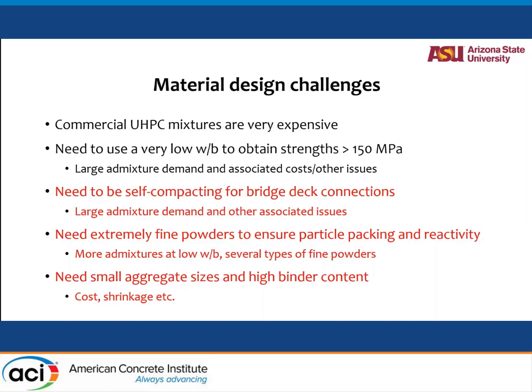They need to be self-compacting for bridge deck connections. You're looking at small volumes and closely packed areas that it has to flow into. You need extremely fine powders to ensure particle packing and reactivity. That will again influence the water binder ratio, admixture contents, etc. And we also talk about small aggregate sizes and high binder content. Most commercial UHPCs that are used are mortars, basically cement sand mixtures with a bunch of other particles. But we also now develop small aggregates into UHPCs to ensure volumetric stability and also to control the cost a little bit.